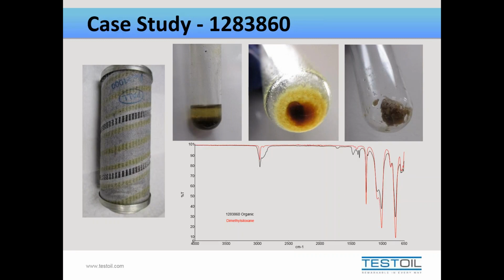So at this point, unfortunately, there was no easy way to just isolate the silicone within the system and get it out and just continue with the ethylene glycol lubricant they had. But most likely they had to flush the system and charge it with a new fluid. But in the future, it was also recommended that routine oil analysis be used, because this is a problem that most likely could have been detected by routine oil analysis if they had used it.